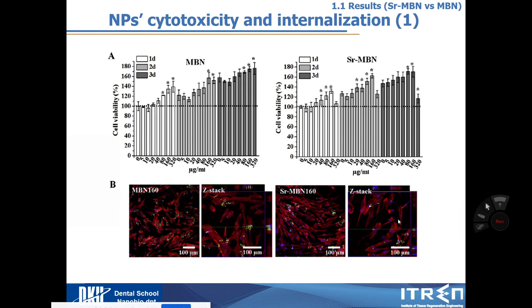And then I started to do some cell work. Over a range of concentrations, I treat the nanoparticle to human dental pulp stem cells. Over time, 1 to 3 days, it shows more or less similar cell viability, which means they don't have any cytotoxicity. But in the case of MBN, at 3 days, 320 microgram per ml starts to show cytotoxicity compared to the control of 0 microgram per ml. So I chose up to 160 microgram per ml for the next study.